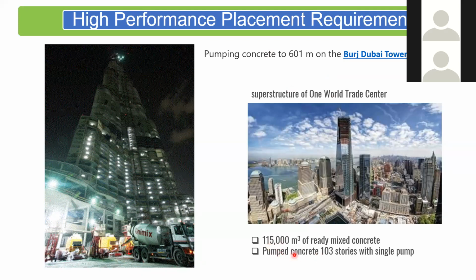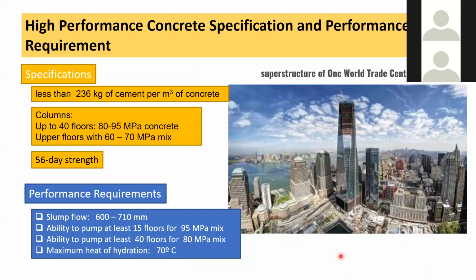So here, in fact, if you look at One World Trade Center, concrete is pumped to 103 stories. And in the next slide, I'll show you the performance requirements that were put in place. This is the performance requirements put in place for the One World Trade Center. This is a building that replaced the World Trade Center, the Twin Towers. Here the specs were that one could not use more than 236 kgs of cement per cubic meter. This was specified. The contractor could not use more than this. Concrete that went into the columns up to 40 floors was required to meet the strength requirement of 80 to 95 megapascal. And in the upper floors, concrete had to meet a strength requirement of 60 to 70 megapascal. Of course, this is a 56-day strength that was specced out.